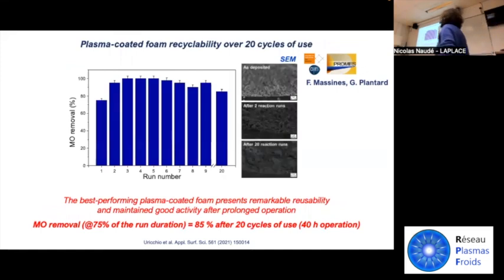Again, what about the recyclability? Of course, it's really complicated to obtain a really, let's say, eternal photocatalytic material. But in our case, it seems that the results are quite promising. For instance, we observed that the best performing plasma coated foam presents remarkable reusability and maintains good activity after prolonged operation.